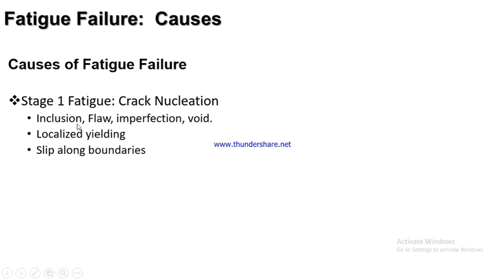It will also have what we call localized yielding. Localized yielding can also initiate fatigue, especially when those flaws are there and the material is subjected to cyclic loading. We can actually have localized yielding begin to take place. We also have slip along boundaries, which can also initiate fatigue, because even when there are no inclusions, because we try to avert inclusions in the processing history of the material, or design against them, we find that during usage or in service, when the material is subjected to cyclic loading, it can lead to slips along the grain boundaries of the material, which basically leads to crack initiation and crack growth.